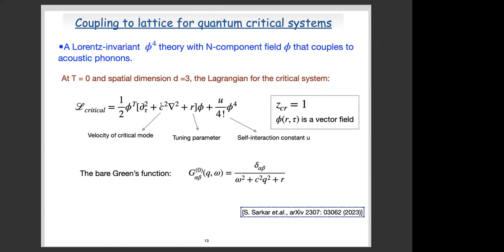So we consider a Lorentz invariant phi-4 theory with an n-component field phi that couples to the acoustic phonons. And we are at a quantum critical system, so at T equal to 0, and we are at d equals 3. The Lagrangian for this critical system is given by this equation. Here is the dynamic part, the kinetic part, and c is the velocity of the critical mode, r is the tuning parameter of the phase transition, and u is the self-interaction constant. As it is Lorentz invariant, the dynamical exponent for this critical mode is 1, and these phi fields are basically vectors.